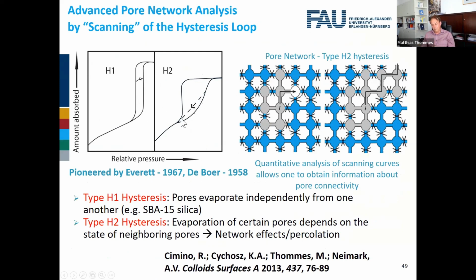Therefore you see that this desorption scan curve is completely different from the boundary curve. So this indicates that when we only fill the particle to a certain extent, we remove the pore blocking effect. By analyzing such data in a systematic way, which was pioneered by Douglas Everett, de Boer, and many others, you can get information about pore network connectivity and other things.